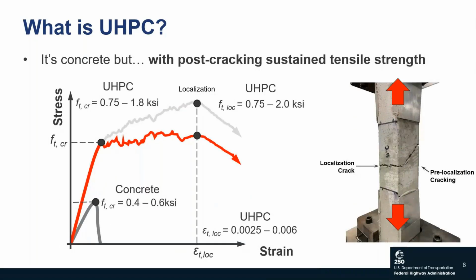More importantly, though, and where UHPC stands in the realm of conventional concretes is its ability to carry tension. Not only can it carry a high tensile strength, but also it can sustain that after cracking. What I mean is, if we take a stick of conventional concrete and you apply tension on it, you will see that it will carry some tension, maybe a stress around 0.4 to 0.6 KSI, that's typical. However, then it cracks, and once it cracks, it splits into pieces, and then the load directly drops down to 0.